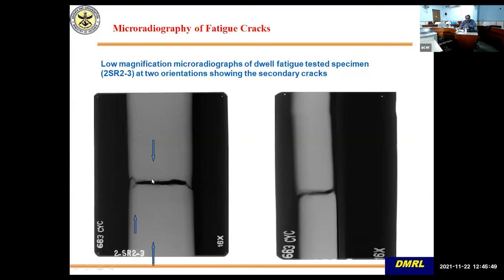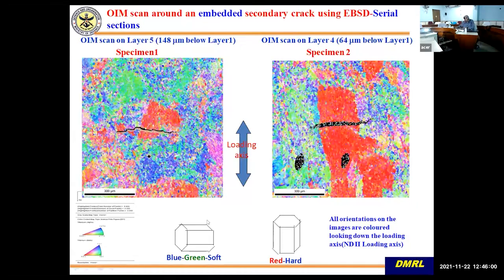This is the main crack, and these are fine secondary cracks which are there. It was imaged in two directions, and my job was to look for texture around the crack. This is a secondary crack which is there. So I polished up to the secondary crack and then took the EBSD map. You can see this is the loading axis in the flat. I kept the track. So this is the loading, and this is the secondary crack which I'm showing you.